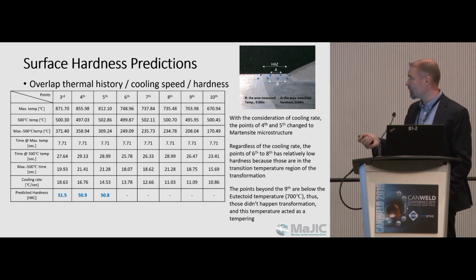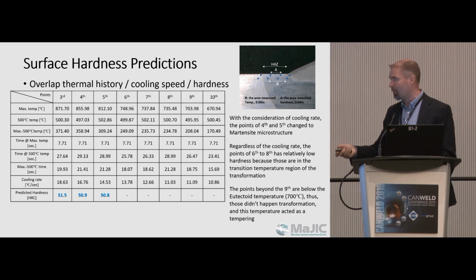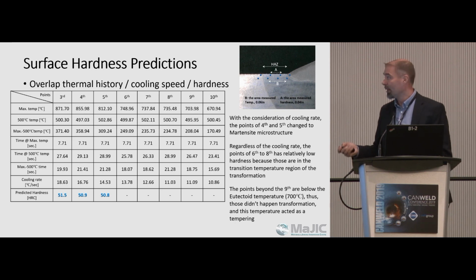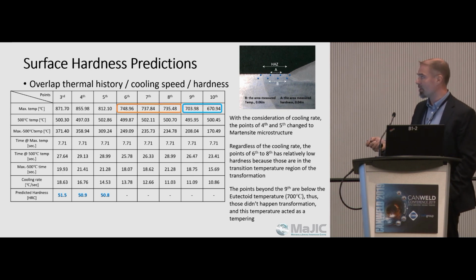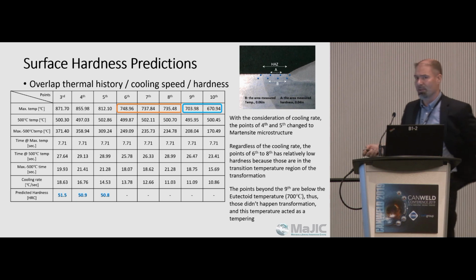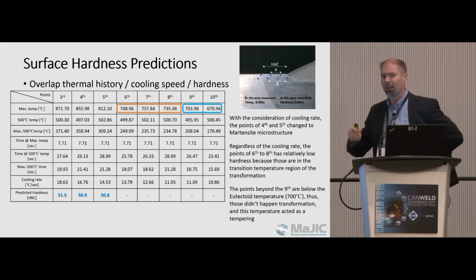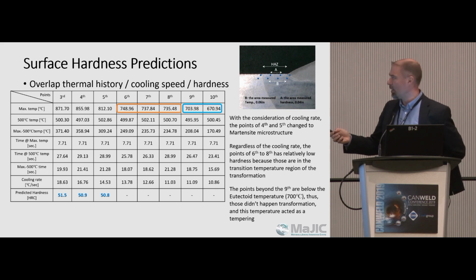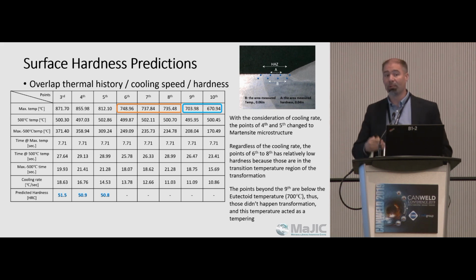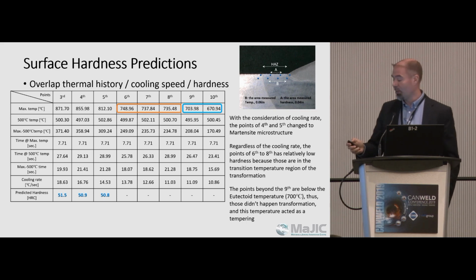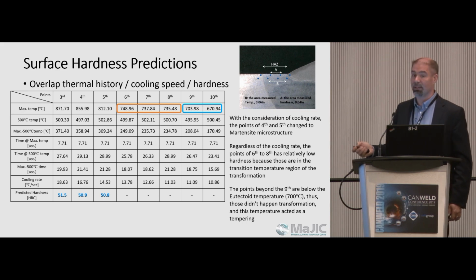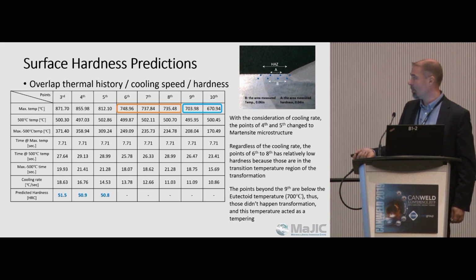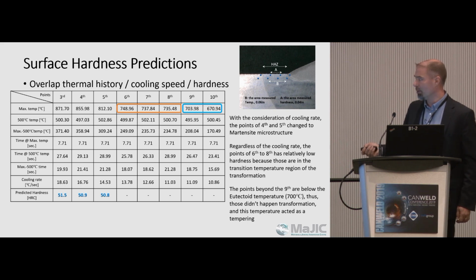So our surface hardness predictions, we came up with some, based on all this information straight out of the thermal camera, we came up with some predictions in the low 50s, right around 51. Okay, in these areas here, these measurements, there's 6th through the 10th data points, we didn't make any predictions, primarily because we didn't get into the transformation zone. We didn't get hot enough to fully transform into austenite. So based on the rapid heating cycle and the rapid cooling, we were not expecting any martensite in these areas. Okay? So back to our prediction, we were pretty close.